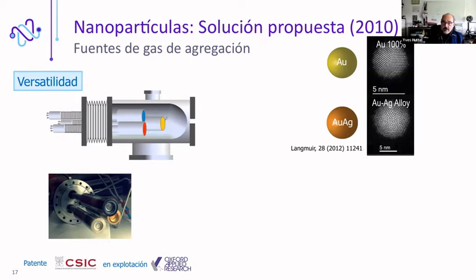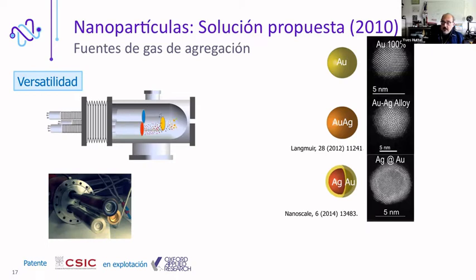But the advantage of having these magnetrons that can be placed at different distances from the exit of the aggregation zone is that we could place the red magnetron behind, nucleate the red atoms in a nanoparticle. Then when it passes through the plasma of the second magnetron, it's covered by the atoms of the second magnetron. This allows us to form core shell nanoparticles in a single step without the need of annealing or post treatments.